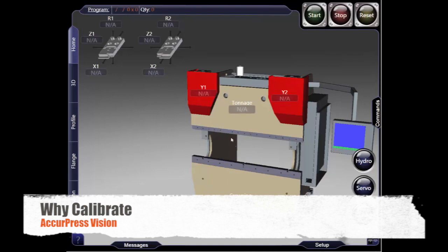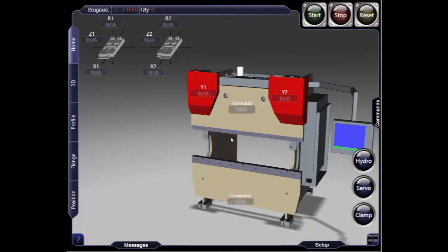If you plan on doing precision bending, you need to calibrate your machine to get the maximum results. The Vision machine comes with a standard material database that was produced with press brake tooling that you may not have. So to get the best results, we need to do several test bends with the material and tooling you plan on using, and to every gauge you plan on bending.